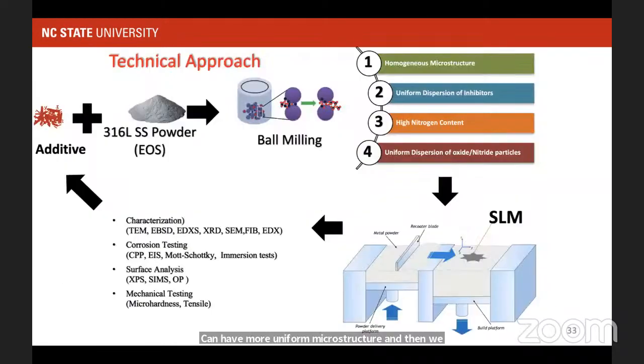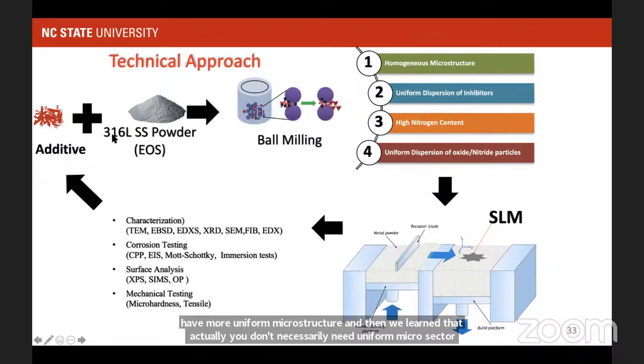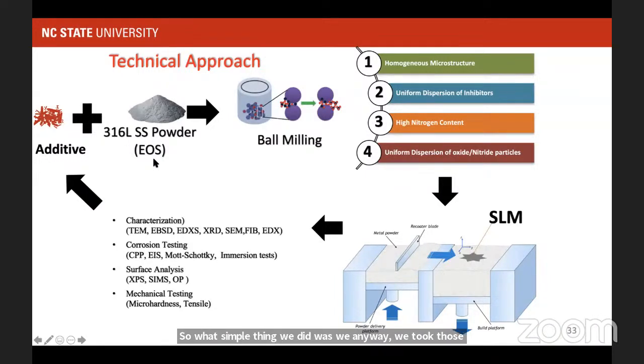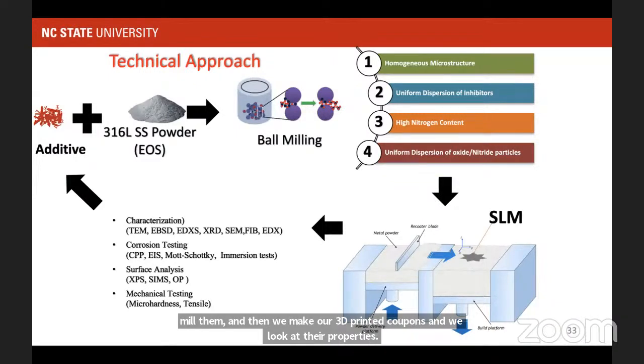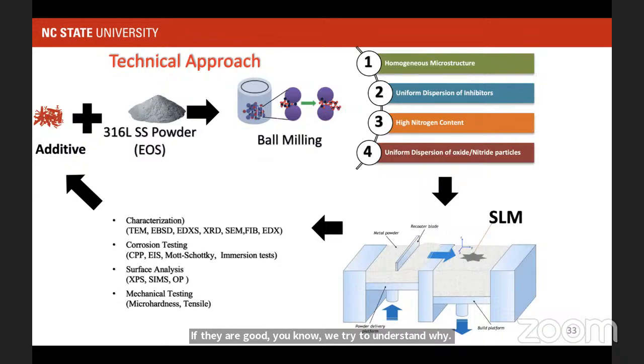So what simple thing we did was, we took those additives and milled them with the 316 stainless steel powder. We buy them from commercial vendors, mill them, and then we make our 3D printed coupons and look at their properties. If they are good, we try to understand why, what the mechanisms are. If we didn't get the result, we of course try to understand what happened, and then we repeat the process. So there's lots of experimental work.